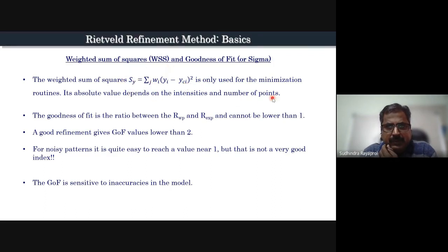This is used to minimize in the subroutines. We should always keep an eye on how the chi-square is varying. It should progress in a particular direction. It should come down from your initial fit. So the goodness of fit is the ratio of RWP to R expected and cannot be less than 1. A good refinement has goodness of fit values lower than 2 or around 2. For noisy patterns, it is quite easy to reach a value near 1, but it is not a very good index. And goodness of fit is sensitive to inaccuracies in the model. So if there is some problem with your starting model, you will never have a good goodness of fit value.